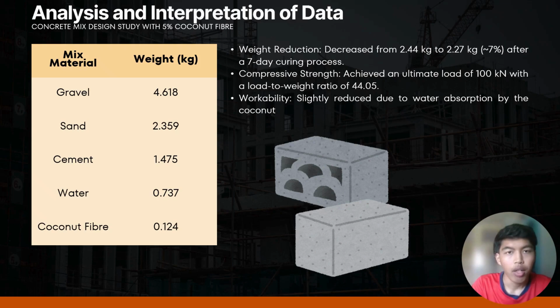For our concrete mix design, coconut fiber was utilized as the aggregate replacement material. The chosen replacement percentage was 5%. The casting took place on the 24th of June 2026 and the curing process commenced on the 25th of June 2026. The mix consisted of 1.475 kg of cement, 2.359 kg of sand, and 4.618 kg of gravel.